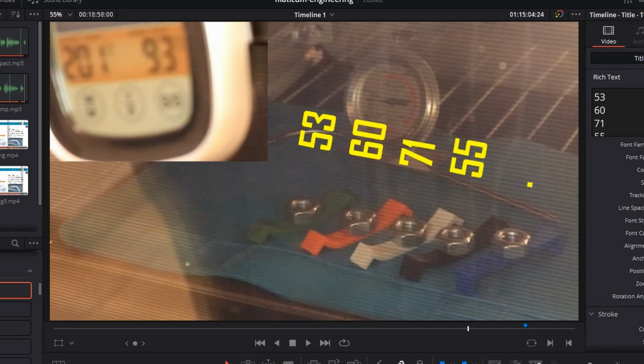And now the conclusions. Well, actually I'm on holiday now, but everything was recorded before my traveling. Definitely the best PLA filaments I tested so far, with all those advantages which regular PLA has. So that's a very strong material, except its biggest problem is the temperature resistance and the creeping. Now the PLA Advanced has extremely good layer adhesion. The start of deformation was just a little bit above regular PLA, but then it stopped deforming, and at the end actually it was stronger, better than regular ABS.